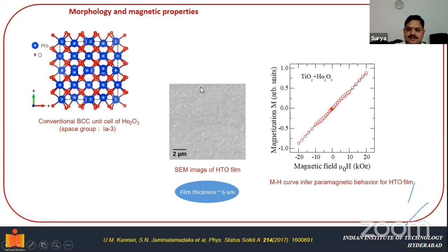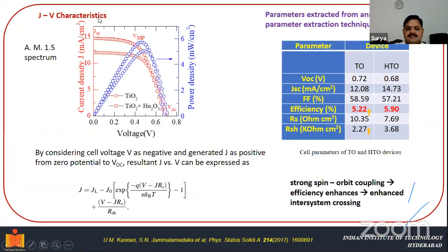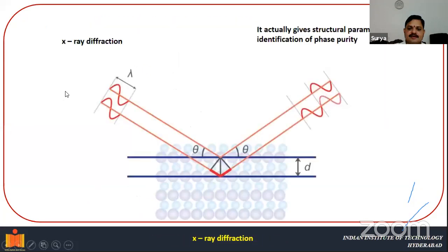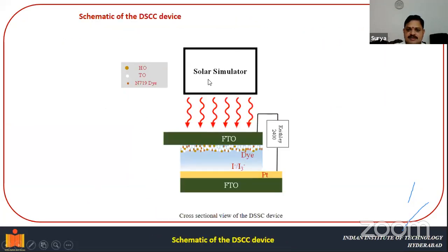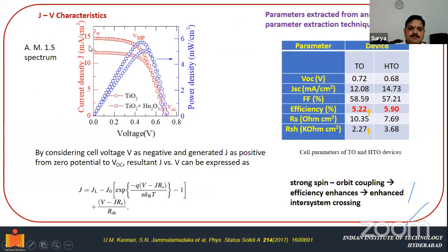This is the surface morphology that we have obtained from the SEM. The surface resembles very smooth, without any discontinuity, and the film thickness is about 6 micrometers. And these are the JV characteristics, the current density versus voltage, that we have obtained for the HTO device, the holmium added titanium dioxide based device. Here we used the AM 1.5 spectrum. As I mentioned, we have to impinge a light on top of the solar cell, so we have used the AM 1.5 spectrum.